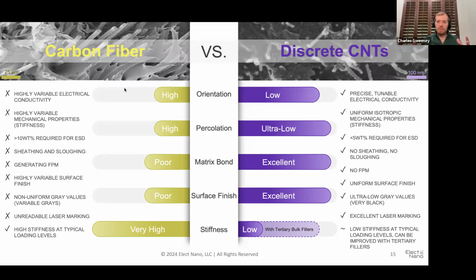So if you have chunks of carbon nanotubes all over the place, and those chunks are micron sized, you're back to square one. You've got hot spots, cold spots, and it doesn't really solve the problem. And so a lot of the off-the-shelf carbon nanotube master batches that you can purchase today are reactor carbon nanotubes that have been compounded into a thermoplastic, but you look at it under a microscope and it's like Rocky Road ice cream, chunky monkey. You've got chunks of carbon nanotubes all over the place. Degree of dispersion is fairly poor.